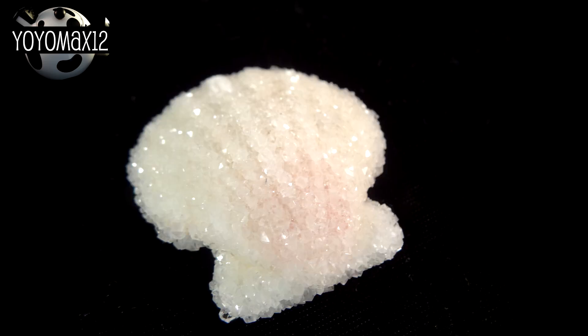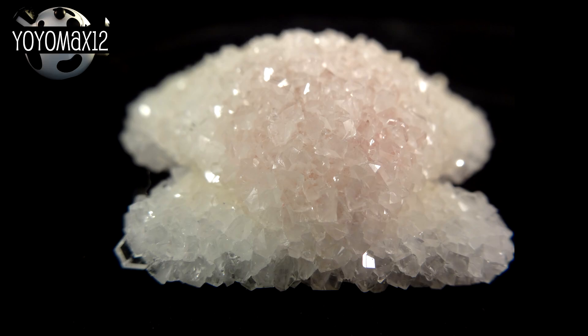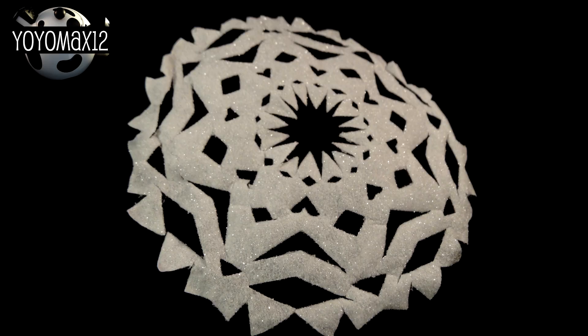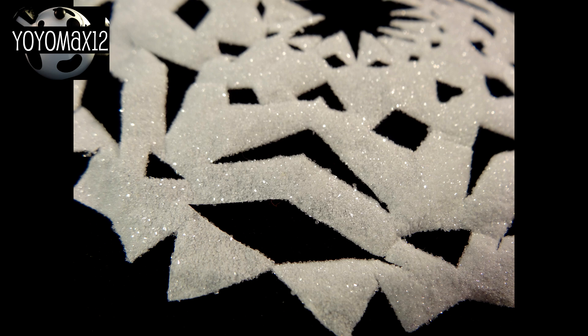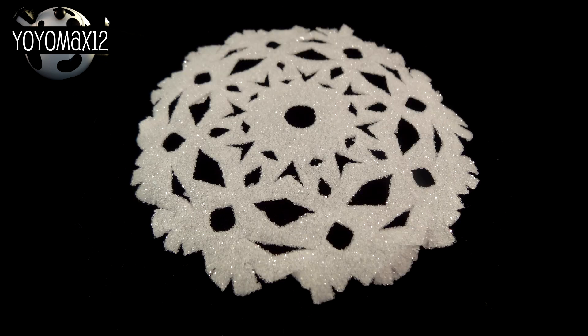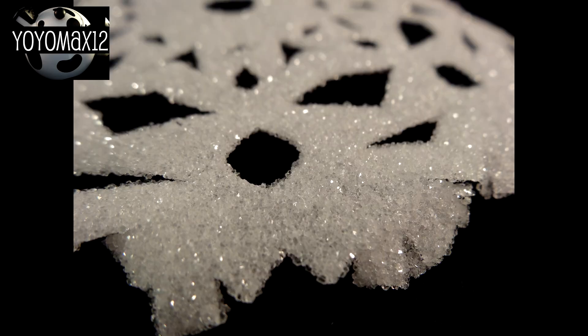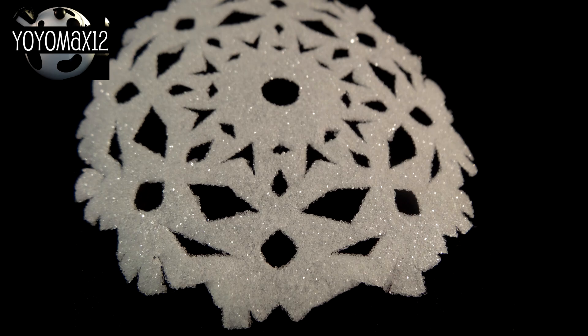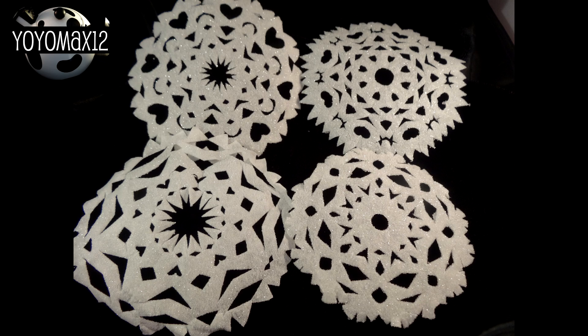Now for seashells, keep in mind that this works well with rough seashells. I tried this with a super smooth shell and they didn't work very well with the super smooth shell. This is a snowflake that was let sit for one hour. You can see the crystals are tiny. This snowflake I let sit for about three and a half hours. The crystals are a lot bigger and it's a lot more sparkly. And this one I let sit overnight and there wasn't a whole lot of a difference between the four hour and the overnight for that one.